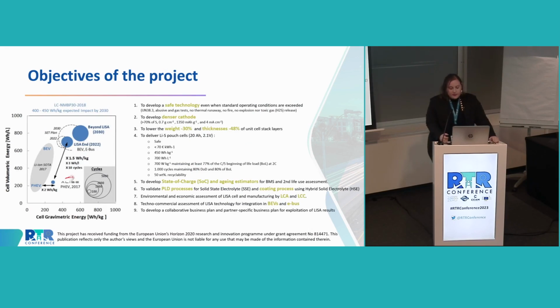The objective of this project was basically to obtain a safe lithium sulfur battery that goes beyond standard operation. This means abusive testing, thermal runaway, gas release, etc. To develop a layer-by-layer battery with a denser cathode with high sulfur utilization, obtaining more than 400 watt-hour per kg and 700 watt-hour per liter, with more than 1,000 cycles, to develop state of charge and aging estimators, to validate the pulsed laser deposition for this layer-by-layer battery, and finally to assess the integration of this battery into e-buses and electric vehicles.